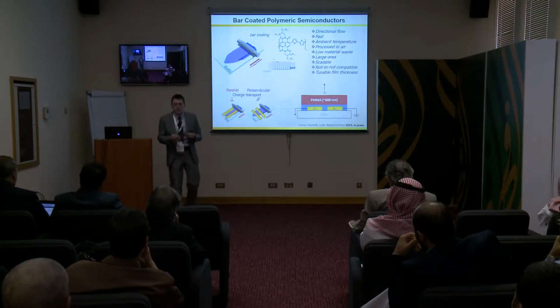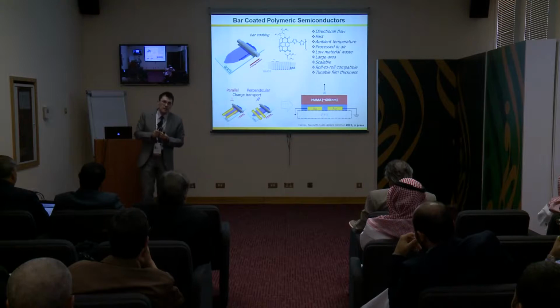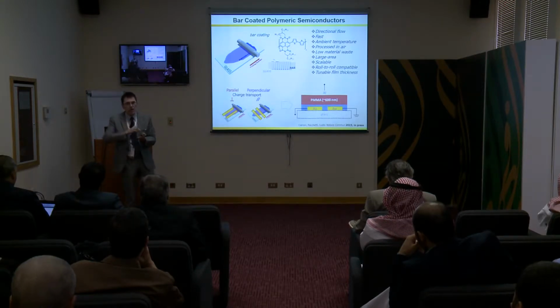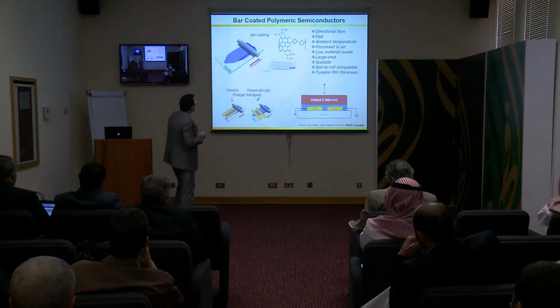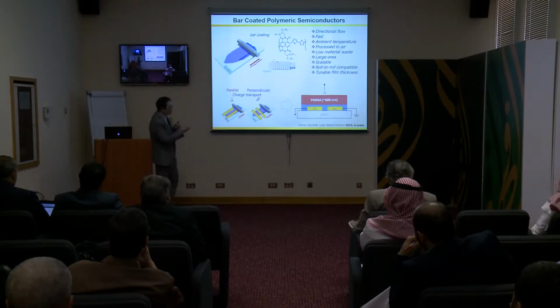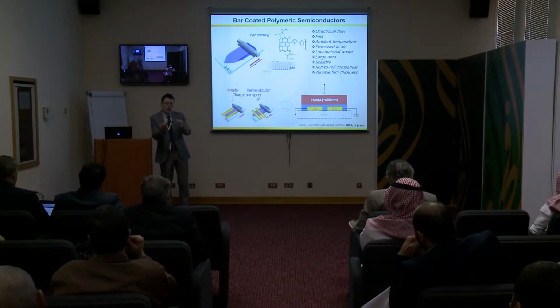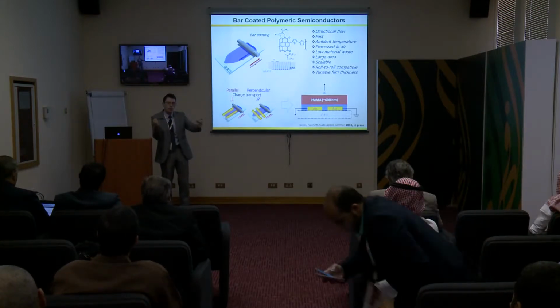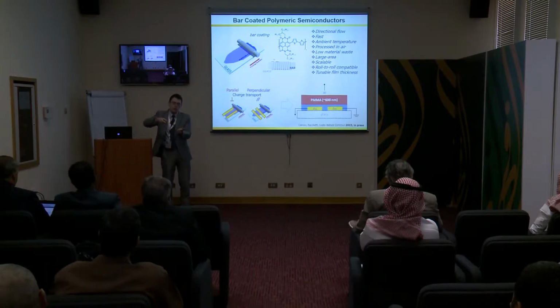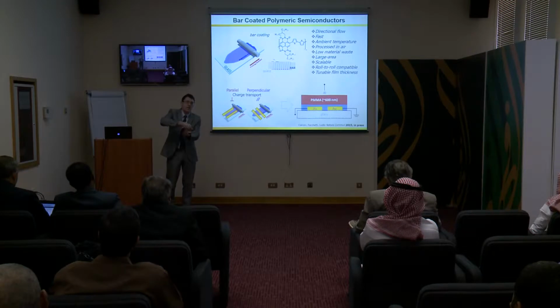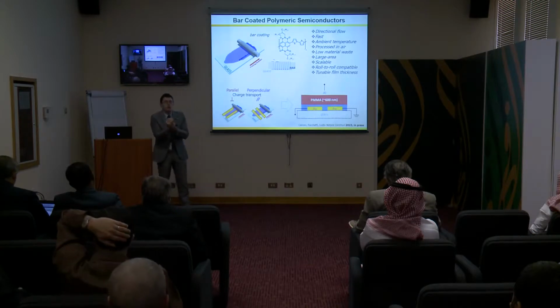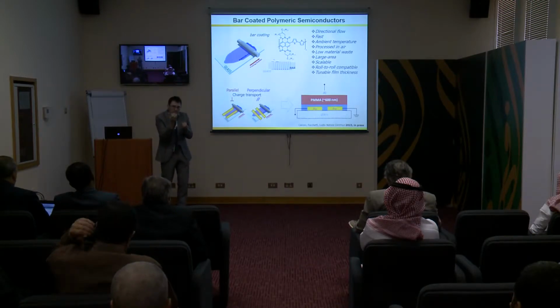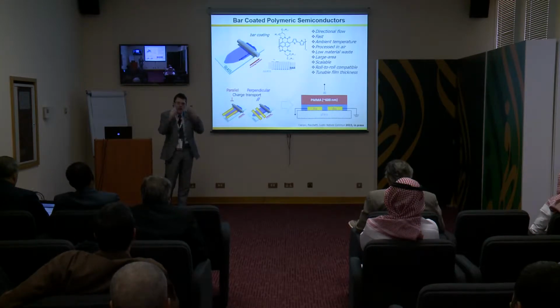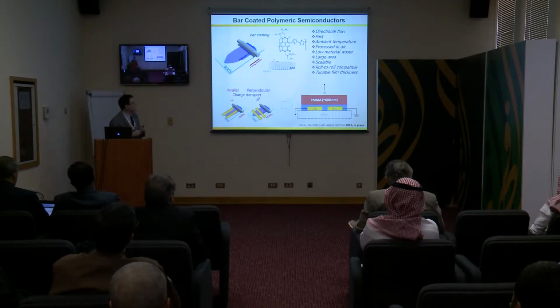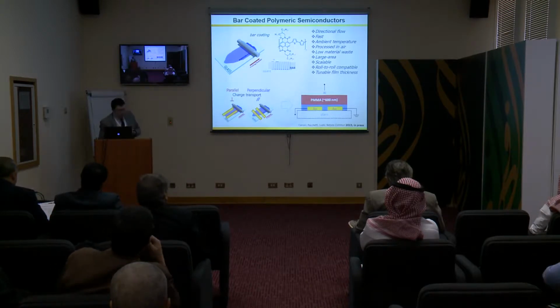Another effective way to print is one that doesn't pattern, but it prints. It's called slot die coating or bar coating. And the uniqueness of bar coating is that, especially for polymers, you have your high molecular weight macromolecules, and slot die coating or bar coating is a sort of sliding technique. So you can think about these rods, these polymers getting aligned during the printing. So the question is, can we take advantage of the alignment because of the printing methodology to achieve higher performance compared to other techniques, which are typically spin coating? And